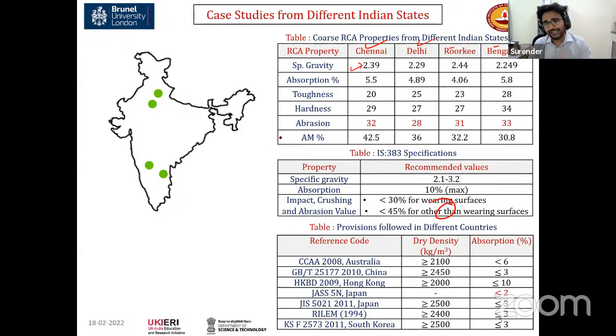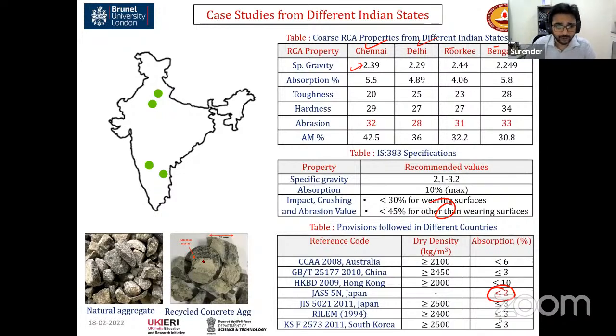If we compare our guidelines with the provisions followed in different countries, we see that some of the countries are too stringent. They ask for 2% water absorption, but we know the water absorption of recycled concrete aggregates is significantly higher. Why is it so? It is because of the added mortar content.